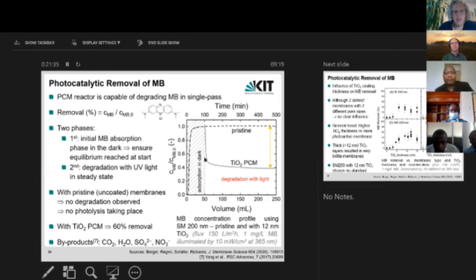This is just to allow the system to equilibrate, and any methylene blue that wants to adsorb in the system can. Then at time 100 minutes, which corresponds to a volume of 50 milliliters being passed through the system, we turn on our UV LED, and then you can see two curves. The solid curve is dropping quite steeply. That's for our titanium dioxide coated photocatalytic membrane. So this is achieving about a 60% removal in this example.